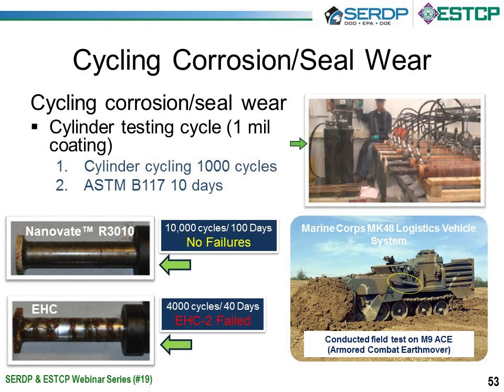What we found in this test is that our product, the Nanovate R3010 product, survived 10,000 cycles and 100 days of corrosion exposure with no failure, no leakage, and no failure of the electroplate with exposed base metal corrosion. Hard chrome plating is illustrated here, and those typically failed at 4,000 cycles. And in fact, in the study, we repeated the chrome plating experiment in parallel with the existing Nanovate R3010, and those also failed prior to any failure occurring on R3010. And that was quite extreme. It was unexpected.